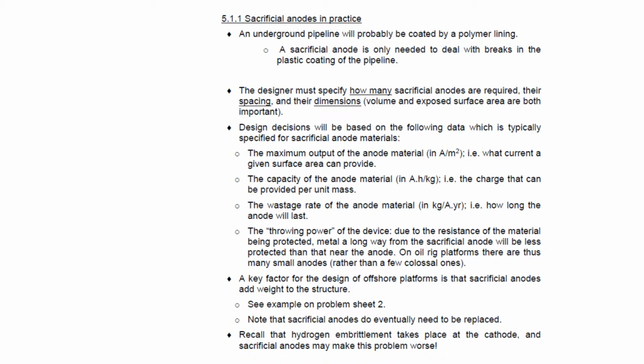One of the parameters you might calculate with then is this wastage rate of the anode material, which is kilograms per ampere. So how many kilograms of the anode, which might be an alloy, is lost for every ampere of corrosion current which it soaks up from the structure.